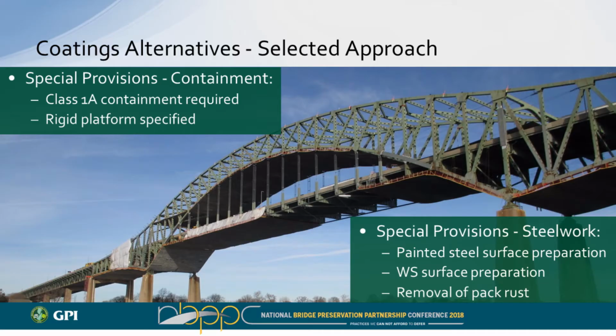So how we specified during design was you would abrasive blast it to an appearance of an SSPC SP10, NACE number 2 from a distance of about 3 feet. So from 3 feet away, if it looks like an SP10 surface, you're good to go. We didn't specify a very specific anchor profile for the weathering steel. And then there was removal of pack rust. So wherever there was pack rust on flanged surfaces, we had them come in and remove it to a depth equal to the thickness. So if you had an inch thick, you had to remove it at least an inch deep as part of your surface prep and your cleaning.